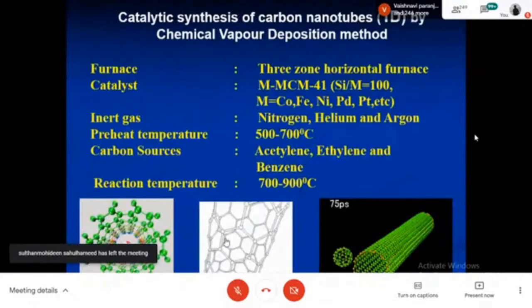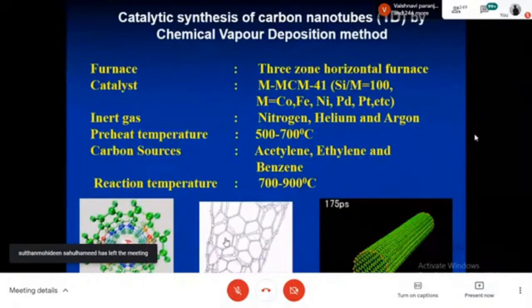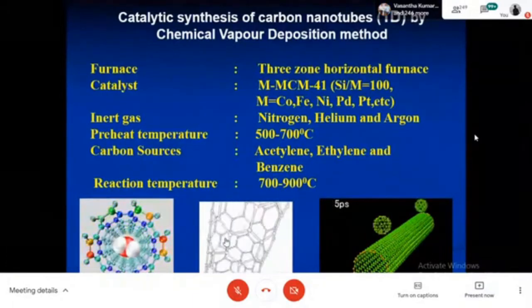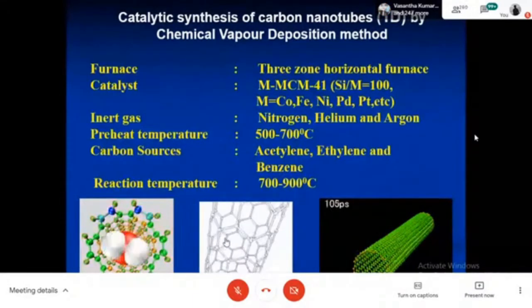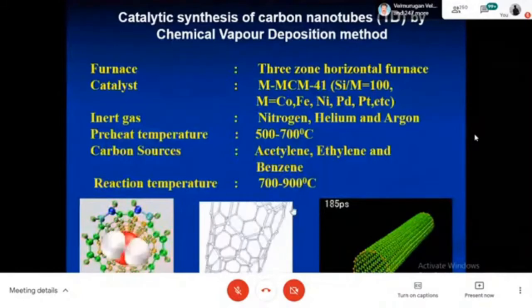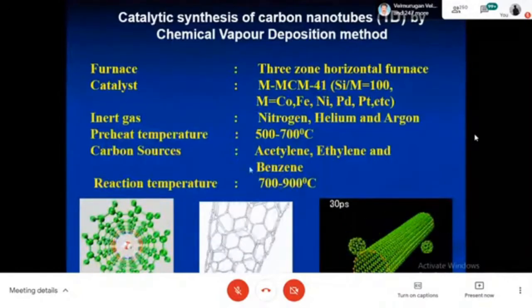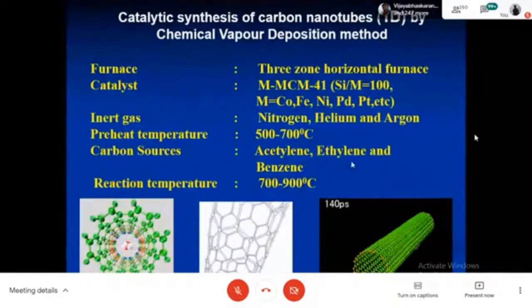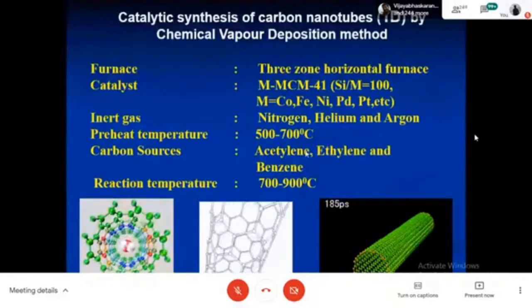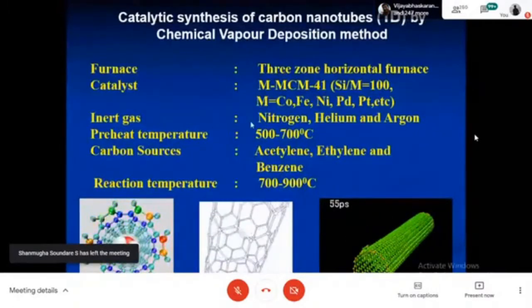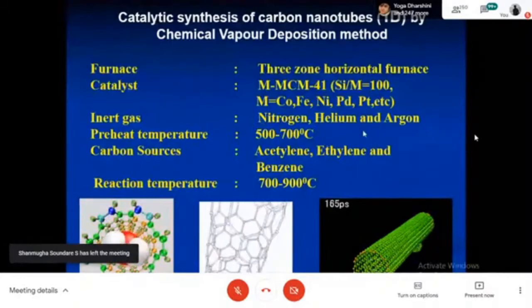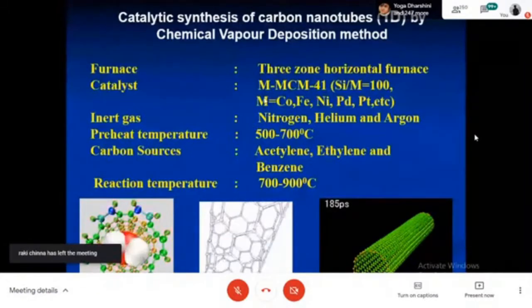There are a lot of synthesis or industrial scale synthesis processes using CVD. And the typical reaction temperature is around 700 to 900 degrees Celsius. And any of the carbon sources like acetylene, ethylene, or benzene can be used, whichever is available in our laboratory. And any kind of inert atmosphere, nitrogen, helium, or argon, can be used.